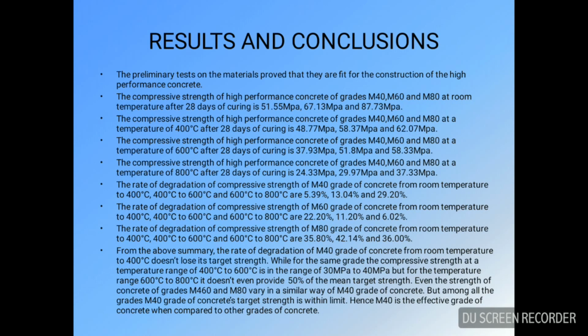As you can see, the rate of degradation for M40 grade of concrete from room temperature to 400 degrees Celsius was around 5.39%. For 400 to 600 degrees Celsius, it came around to be 13.04%. For 600 to 800 degrees Celsius, it came around to be 29.20%. Similarly, the rate of degradation of compressive strength of M60 grade of concrete from room temperature to 400 degrees Celsius came around to be 22.20%. For 400 to 600 degrees Celsius, it came around to be 11.20%. For 600 to 800 degrees Celsius, it came around to be 6.02%.